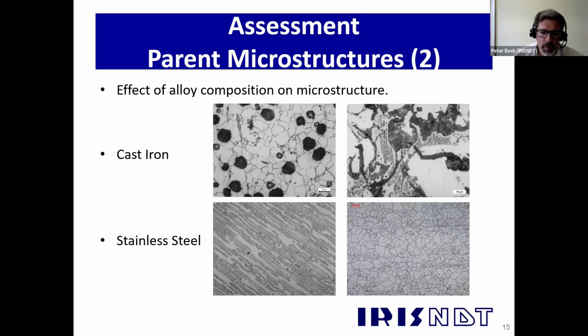The bottom images show stainless steels. Again, different only by their compositions, really. So on the left, we've got a super duplex stainless steel. You can see the light phase in that is austenite, and the darker phase will be ferrite. So it's a two-phase structure there. Whereas on the right, we've got an austenitic stainless steel. So it's a single phase austenite there. You can see the grain boundaries, and you can also probably see some twin grain boundaries as well. So these are the kind of microstructures that we can assess in replicas, and comment on the quality of the microstructure, any degradation, things like that.